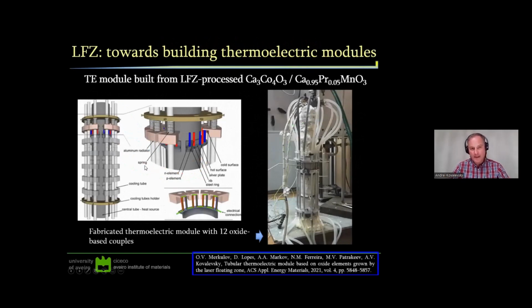The construction of this module itself is very unique. It is for radial waste heat harvesting. The heat source is the tube, and the thermoelectric legs are oriented in parallel to the tube. You can expect that probably a higher temperature difference could be achieved if we made them perpendicular. But this construction actually allows quite significant thermal gradients even in this parallel arrangement, which could result in better specific power because we're saving volume of the module.